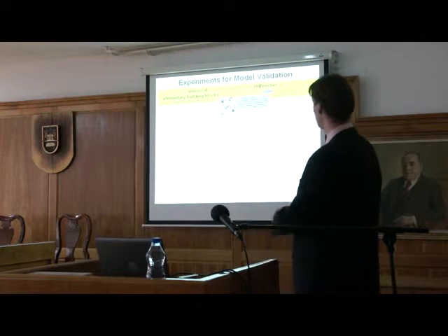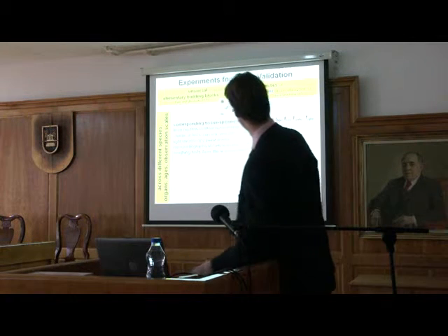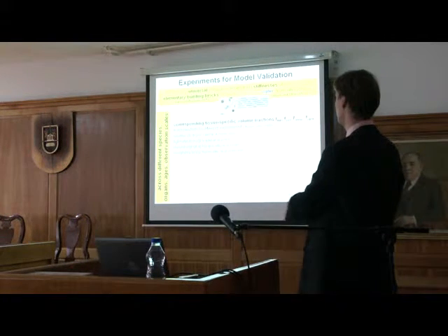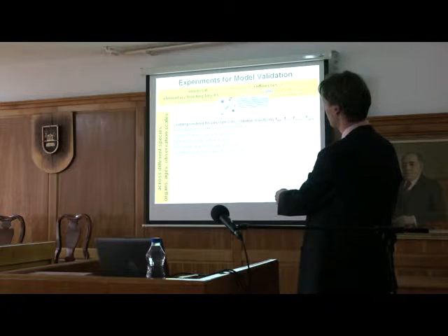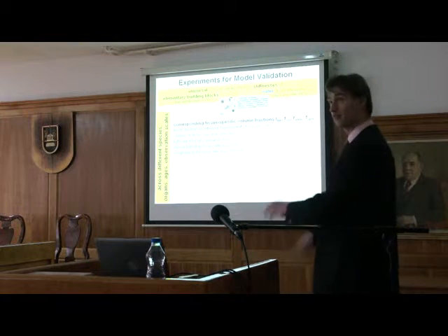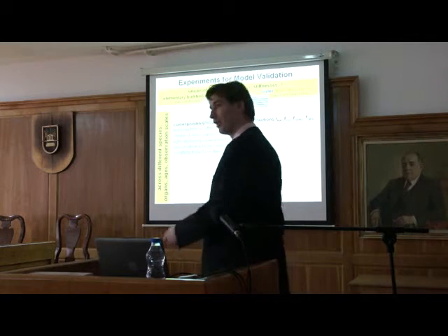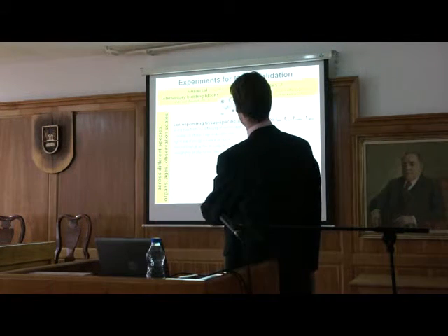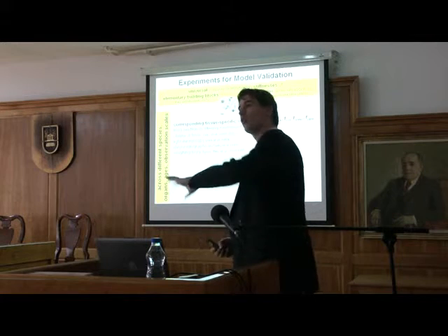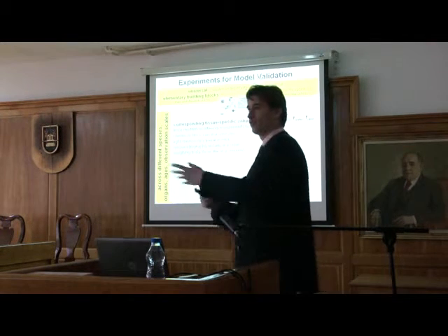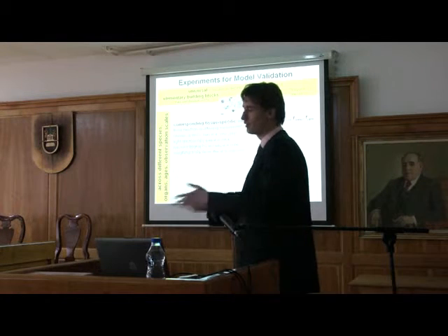Okay, so we need the properties of the mineral and of the collagen, and then we put in the volume fractions. Let's say the stiffnesses for mineral and collagen are the same for each and every bone. And then we have to confront it with a lot of different bones. A lot of different bones means we need all these volume fractions. For example, we can take all the rules from before. We know the mass densities, and from the rules we derive all these different volume fractions.